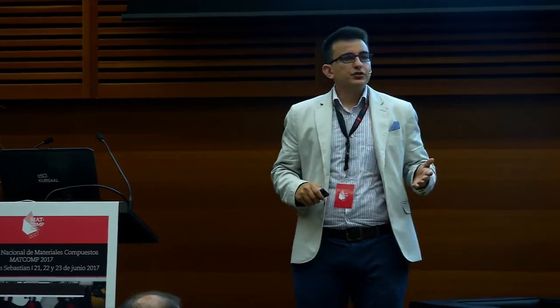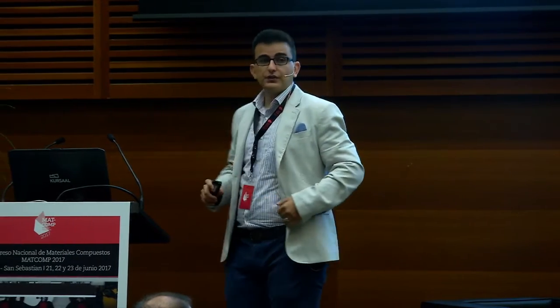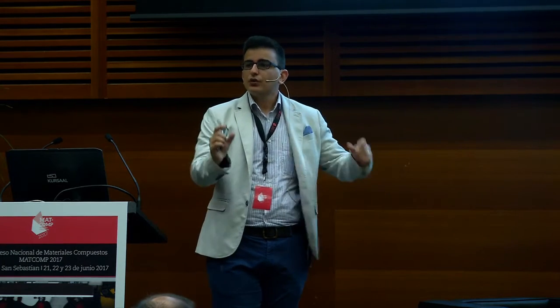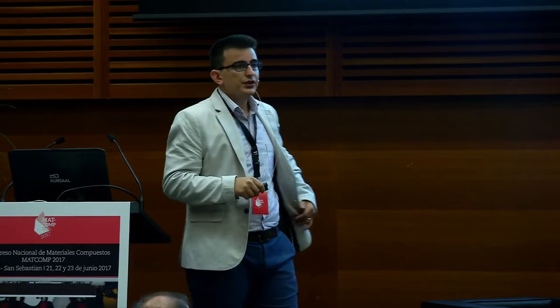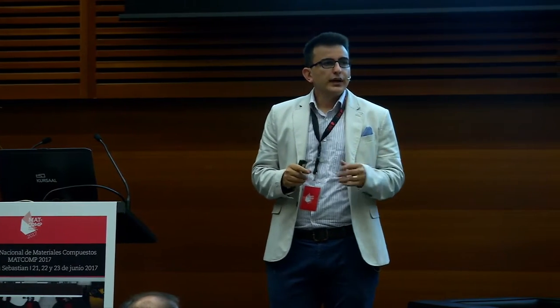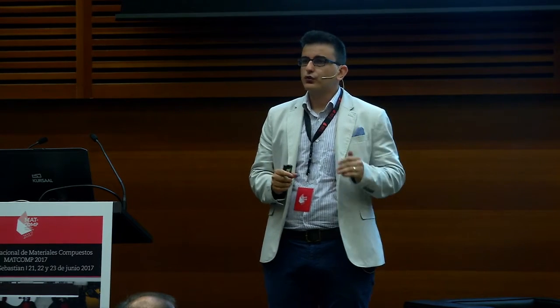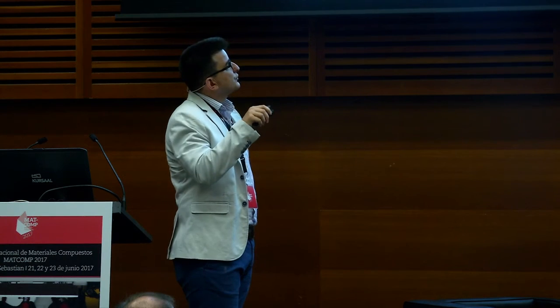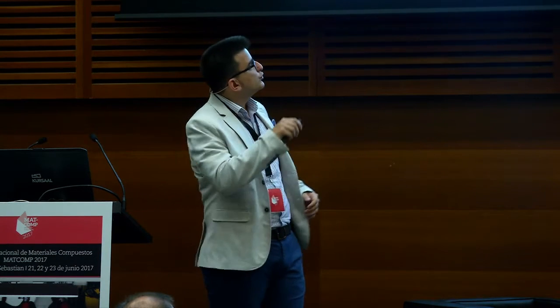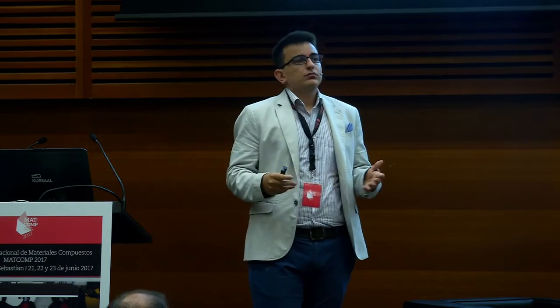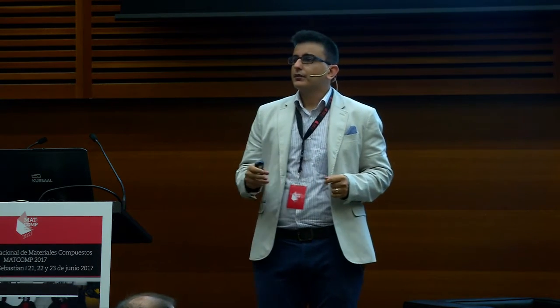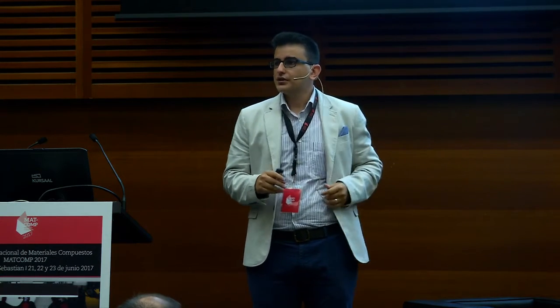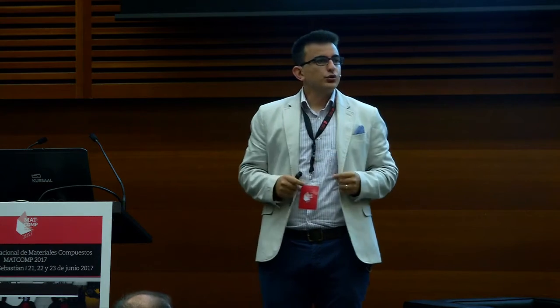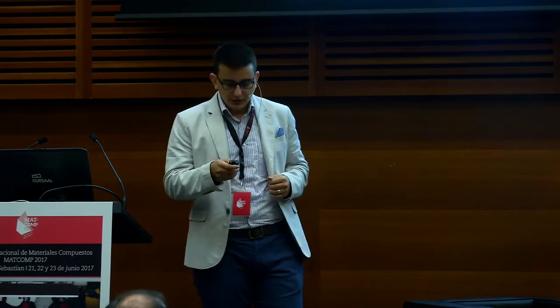Local fiber volume content distribution is very critical, as we saw from the micro-CT images. We have resin-rich areas between roving layers. And here I have an example of a real pultruded profile, relatively thick, 50 by 50 millimeters, full of UD. If we look at a region of interest of 3 by 5 millimeters, we do see severe resin-rich areas between the roving layers. And the question is, in that case, we don't have any crack, but we may have a premature crack. So the internal stress might be that high. So during in-service loading conditions, with a small load, we might have an unexpected catastrophic failure.